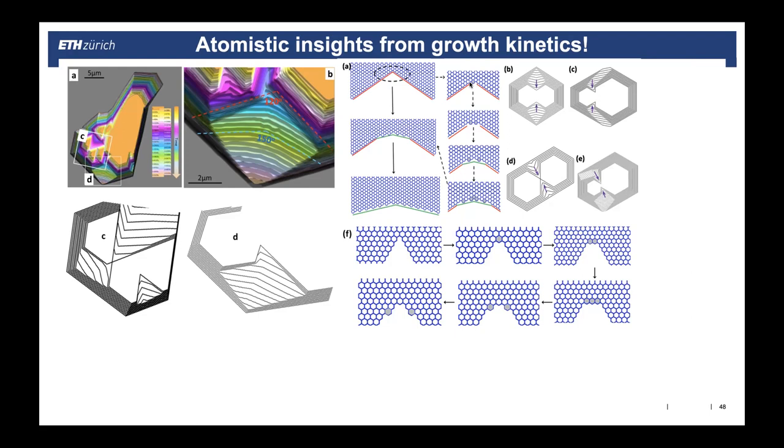And when you continue doing that, you end up with an edge that is the fastest growing, high kink density. We call it the 19 degree edge. As soon as you form this edge here, you grow; this is the fastest growing edge. You know, zigzag edges, they are very stable. They don't grow fast. These are the red guys here. And the green guys, they are the fast growing edges. They fill up that whole space. So we did DFT simulations and it really confirmed this filling at the concave edge.